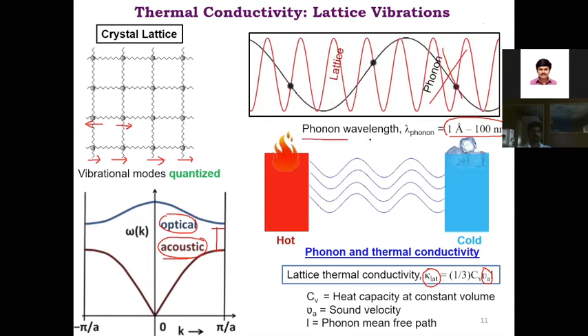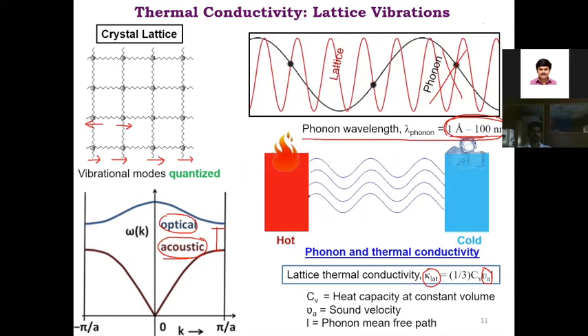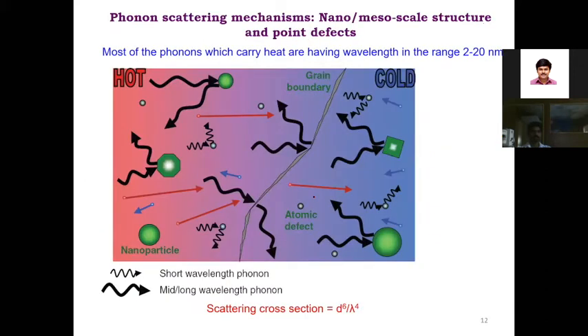Okay, so now how do we scatter this acoustic phonon, which has a wavelength of 1 angstrom to 100 nanometer? This is a cartoon diagram of how phonon scattering generally happens in a solid thermoelectric matrix. The phonons which are 2 to 20 nanometer are the main carriers of heat. 60-70 years back, Russian researchers created point defects. They made solid solutions like PbTe(1-x)Se(x), so they substituted some amount of tellurium with selenium. That creates atomic defects, which are on the order of an angstrom, which scatter short wavelength phonons. But those short wavelength phonons do not contribute much to the thermal conductivity. Phonons which contribute to heat carrying in a solid have a mean free wavelength of 2 to 20 nanometer.